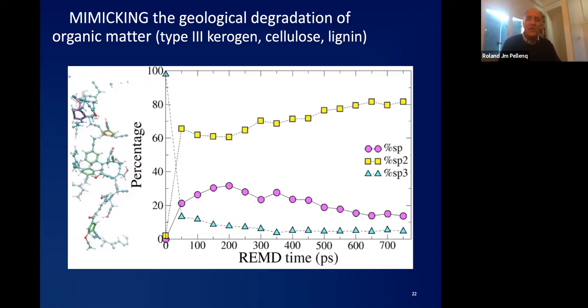And you can see the way those types of bonding are evolving during the simulation. Very interestingly, we start with something which is very much sp3 in the cellulose. Every carbon, that drops down crazy. And then we actually have a production of the yellow, which is sp2, where most of the carbons have three neighbor carbons, in a very graphene-like arrangement, at least locally. Well, you can see there's a very defective structure, of course.